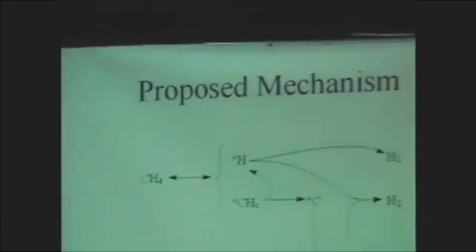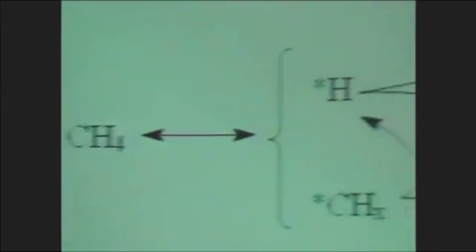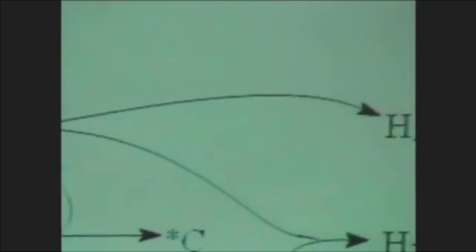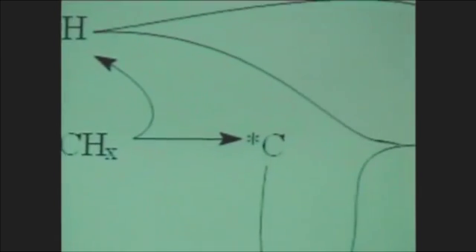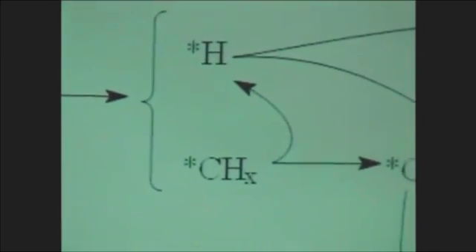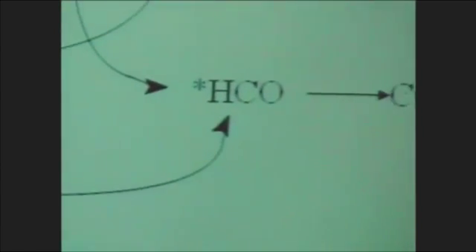So this is a very simple proposed mechanism here. We put a reaction scheme here. I don't want to go into detail because we don't have enough evidence. Simply from our pulsing study, we found out in the reforming of methane by CO2, the hydrogen formation step is a rapid step, and the desorption of CO, in fact, is a rate limiting step. So we always see the adsorbed CO on the catalyst surface.